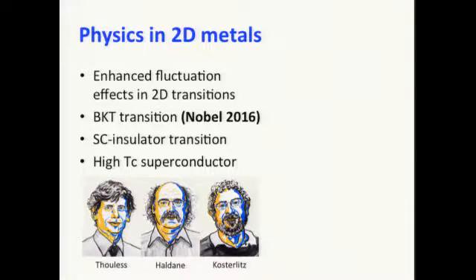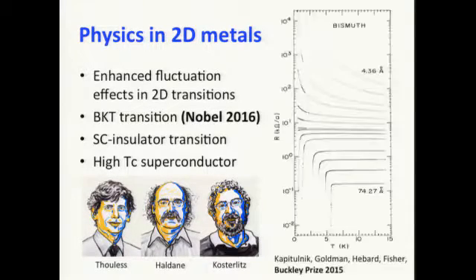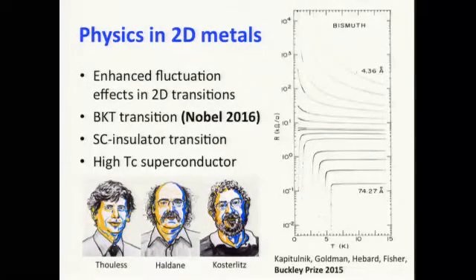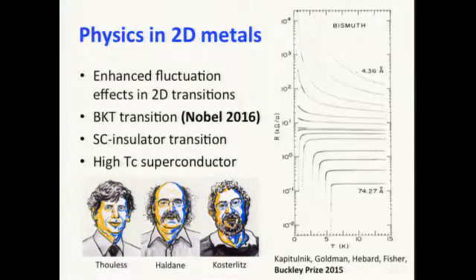Another example, which for the purpose of my talk I would like to give, is the superconductor-insulator transition. I took this beautiful data from Alan Goldman's group, published in the late 1980s. By evaporating bismuth films of different thickness, from 4 angstrom or so up to 7.5 nanometer or so, you can see that over a very narrow range of film thickness, the material turns from a superconductor with zero resistance to an insulator with infinite resistance. This is a very interesting experiment, and lots of work has studied what's happening near this zero temperature transition point.